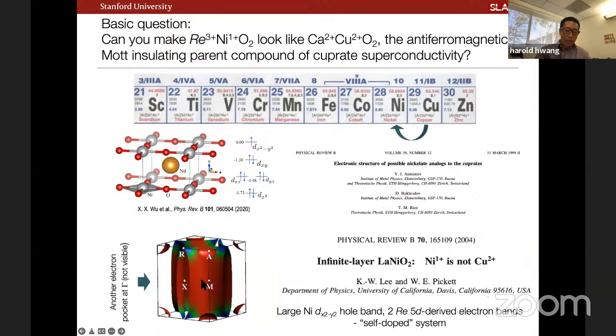There's one at the zone center in the absence of Coulomb interactions that also appears. So it's already quite interesting and rather different, in the sense that you have these two bands, and to a certain degree you can consider this a self-doped system, in the sense that you have charge balance between the electron pockets and the hole occupancy.